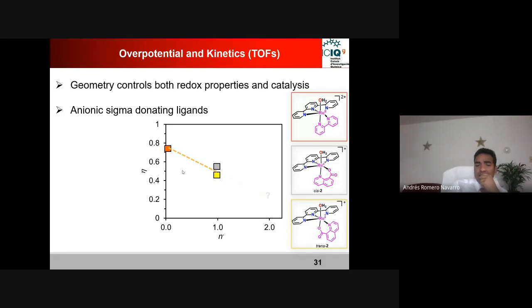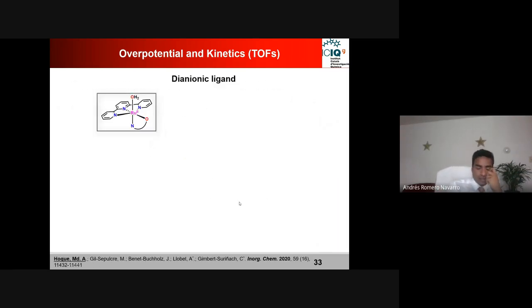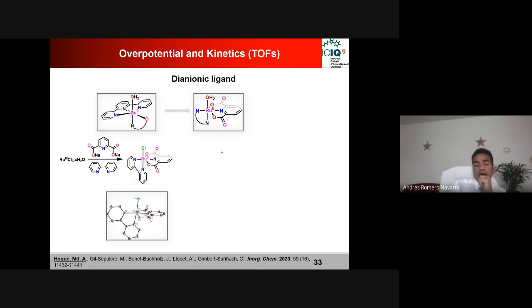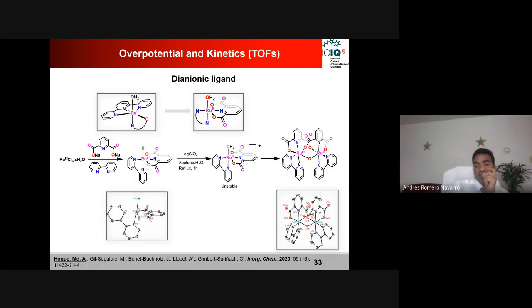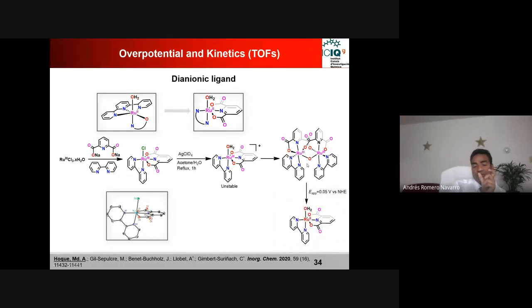Then the question was, can we reduce this overpotential even below that? And we thought, okay, why not try? I tried by considering that we can change from one sigma donating ligand to two sigma donating anionic ligands, that is carboxylate. So we chose this pyridine dicarboxylate ligand and then bipyridine, and I synthesized that one. The goal was to get this ruthenium-3 aqua compound, but we found that this is a very unstable compound forming an oxo-bridged dinuclear compound. But nevertheless, we can reduce this molecule electrochemically, and then we can isolate this ruthenium-2 aqua compound.